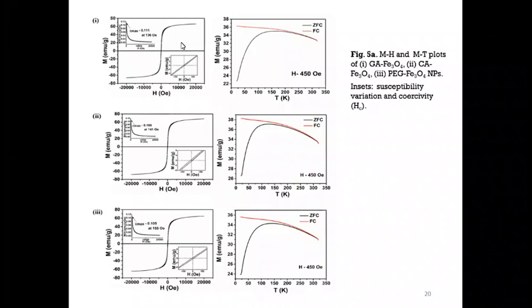Of course, saturation magnetization is an intrinsic property of the materials, and it is 92 EMU per gram for bulk; I have given it in EMU per gram unit. EMU is electromagnetic unit. As it is an intrinsic property, it should not change with respect to the size of the material. However, when it comes to 10-20 nanometers, the surface effect plays a major role, and we have the surfactant also over here. So the orientation of the moments on the surface of the nanomaterials is not like the bulk, due to the difference in the exchange force.